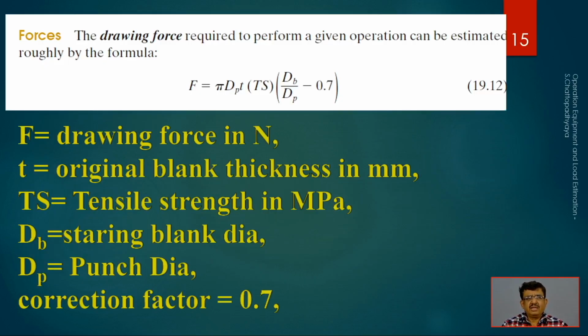The drawing force required to perform the given operation can be estimated roughly by a formula. This is the typical formula, where the force F is equal to pi times Dp, the punch diameter, times T, the thickness, times TS, the tensile strength, times the ratio Db by Dp, the blank diameter over the punch diameter, minus 0.7. A lot of experimentation has led to this formula, the drawing force, and we have to determine it in order to find out whether the machine can deliver that kind of force to get the intended result for the specific case.